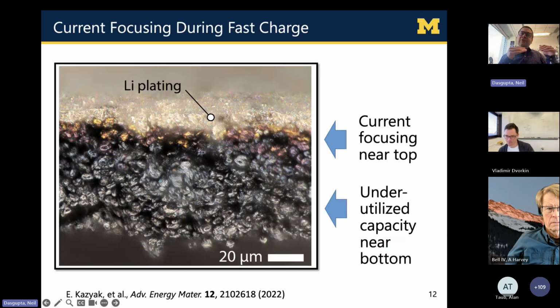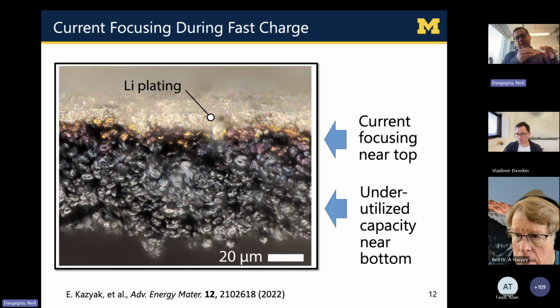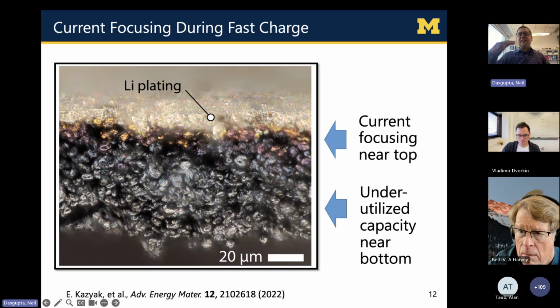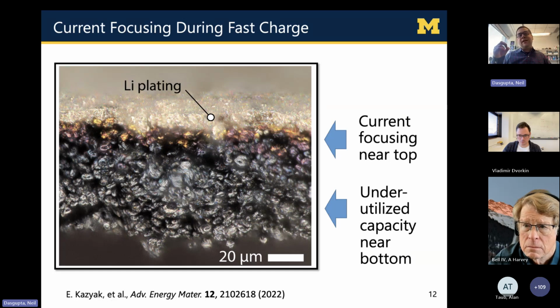So let's take a closer look inside this graphite material. What I'm showing here is a cross-sectional optical microscope image of the graphite electrode after we've fast charged it from our battery. You can see on the top surface this metallic lithium plating, that undesirable side reaction. And notice underneath you see this color gradient. You see these gold colored particles near the top surface that transition to red, to blue, to gray near the bottom. It turns out graphite has this amazing property that it changes color as a function of the state of charge of the particle.